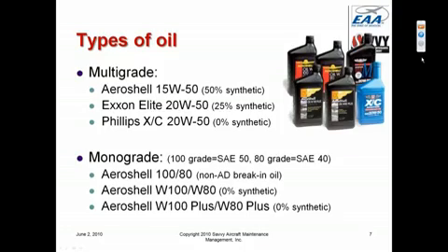Aeroshell 100 or 80 is an oil that is normally used as a break-in oil. It lacks almost all additives. It does not have the normal ashless dispersants that are normally added to operating oils to keep the engines clean and to inhibit sludge. We normally use this oil only for break-in, and we use it more out of tradition than anything else. I've never seen the slightest evidence that a non-AD oil like Aeroshell 100 or Aeroshell 80 accomplishes break-in any better than its operating ashless dispersant version, which has a W on the front of it.